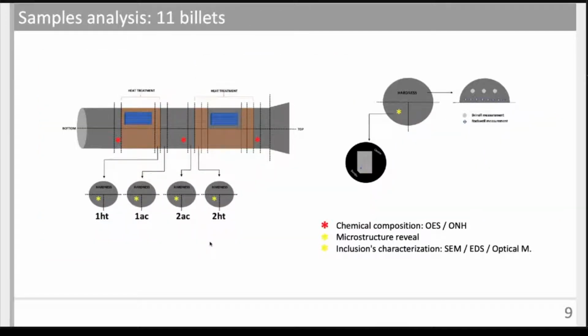So far, we have produced and analyzed 11 bars with different levels of oxygen and different process conditions, as we used the two furnaces, and we also tried something different. In some melts, we checked the impact of not skimming it. Here we have a schematic of the division of the billets that we did in order to obtain all the samples for the analysis. These bars were analyzed in two conditions, as cast and also heat treated. With this analysis, we performed several tests such as Charpy, hardness, we reviewed the microstructure, and we also did inclusion characterization. So now we can check the main findings.